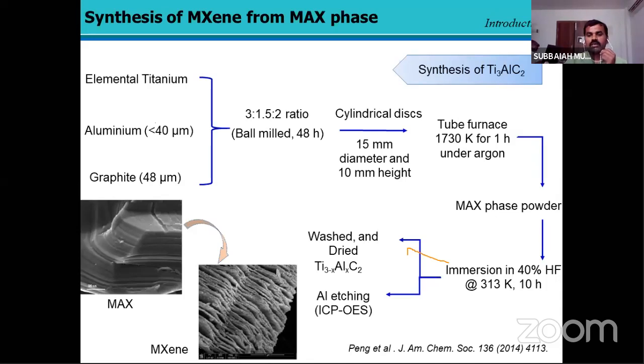This is the bulk form, as shown here on the left side of the image. Then this MAX phase was immersed in 40% HF at 313 Kelvin for 10 hours. The final product was washed, dried, and freeze dried. Then we get the aluminum-removed pieces. The advantage of HF was to remove the aluminum phase to get the exfoliated sheet. That means the bulk phase has an aluminum layer, and the aluminum layer is selectively removed from the MAX phase to get the widely spaced, expanded structure of MXene. When the aluminum etching was done, the aluminum concentration was analyzed using ICP-OES to get the quantitative amount of MXene material obtained.